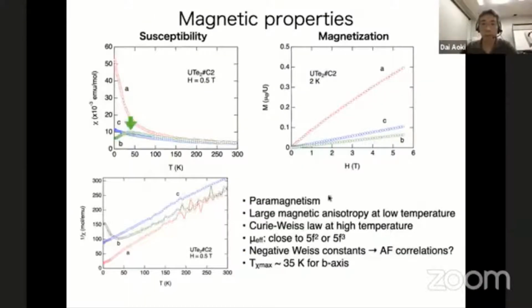Then, the magnetism. Here you can see the magnetic susceptibility and magnetization. For the A, B, and C axes, all directions show nice Curie-Weiss behavior at high temperature, and the A axis is the easy axis. This is the inverse magnetic susceptibility. You can see a nice linear relation. However, if you extrapolate in this direction, you can see the Weiss constant is negative for all directions. From this, we can naively consider that the antiferromagnetic correlation is rather strong.